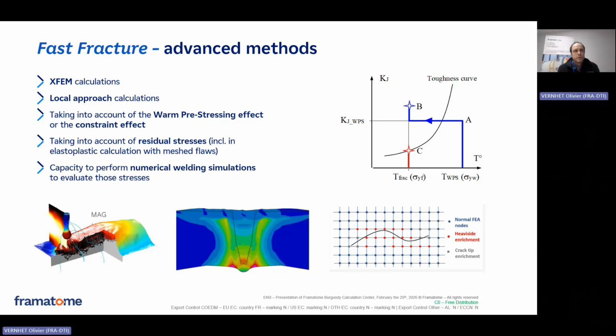Also, another recent approach has been developed regarding fast fracture. I spoke about the global approach before, but Cistus is also implementing a local approach. So we're able to perform some local approach analysis. One application of this local approach is called the warm prestress effect, or the constraint effect, meaning that we are able to say that we can discard fast fracture even if sometimes we might cross the toughness curve, but only if we cross the toughness curve by decreasing the temperature.